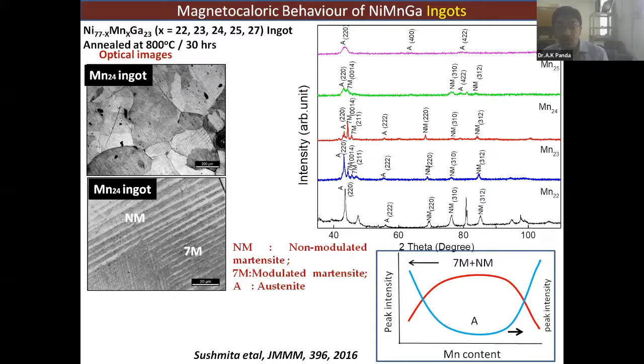In the X-ray reflection, when you go from a low content of manganese to a high content of manganese, you find that initially, at a low manganese content, there is a combination of austenite and non-modulated martensite. At the intermediate stage, it is a combination of both, austenite and non-modulated martensite, and you will see that even the modulated martensite, the 7M modulated martensite, comes into the picture. However, when we raise the manganese to a very high quantity, say manganese 27%, you will end up in more of an austenitic state.